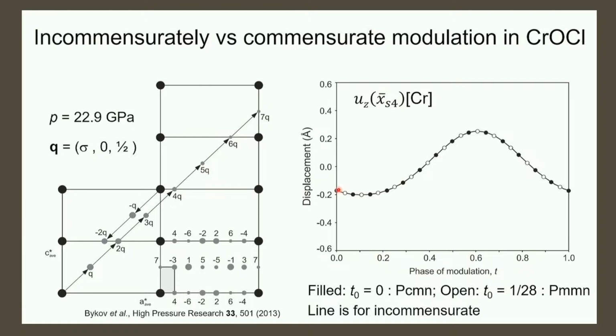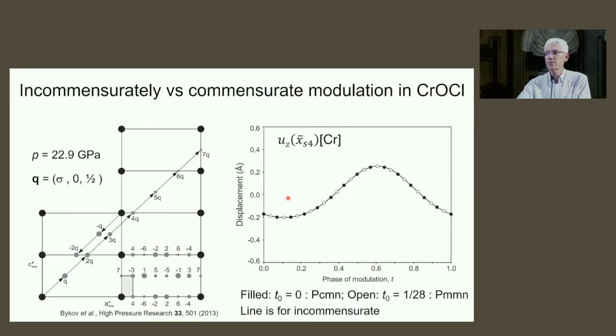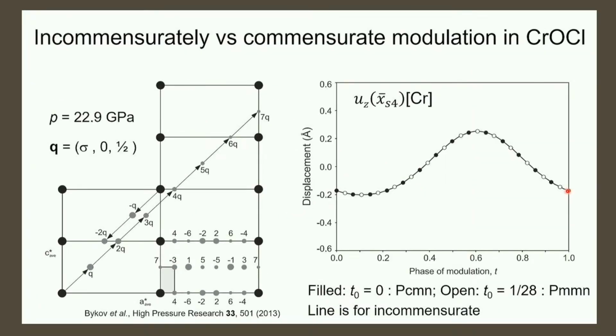And you can imagine, if you now need to compute your structure factor, that just using the black dots or just using the white dots, you already make a very good Riemann approximation to your integral over this modulation wave. So in our structural analysis, sometimes one sees a difference, one fits better than the other, but quite often, especially in such cases, it is very difficult to distinguish the two. Also from a more physical, philosophical point of view, it's maybe important, but not so easy, because one can imagine if we have the black dots, it's actually a similar structure than if we have the white dots.